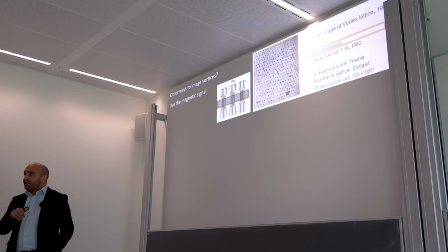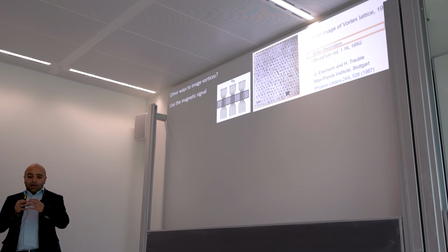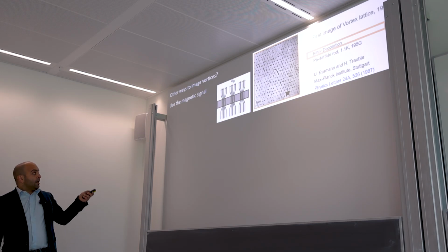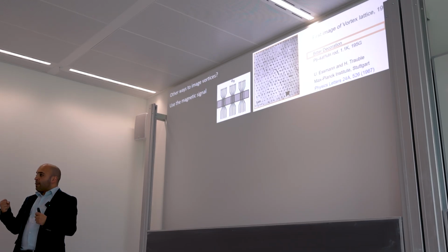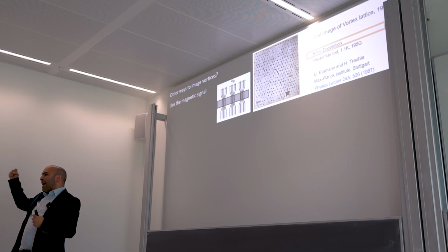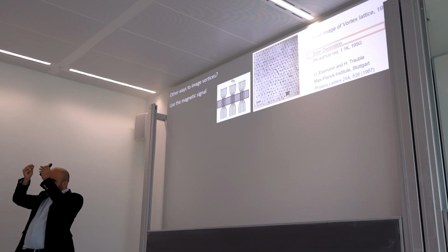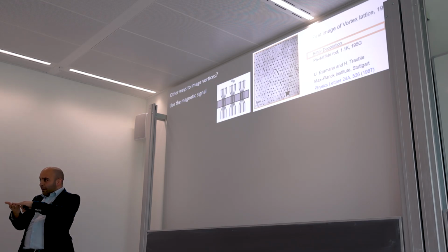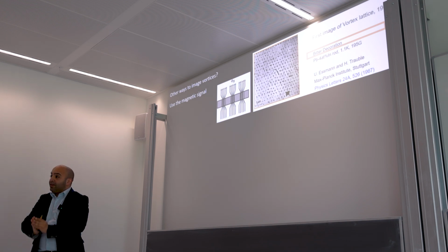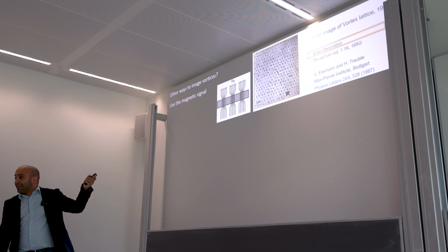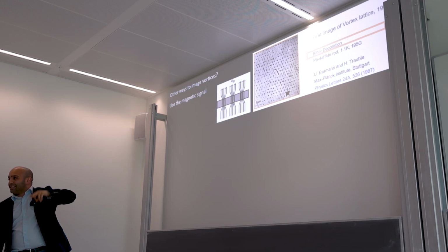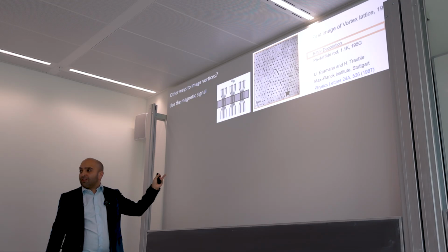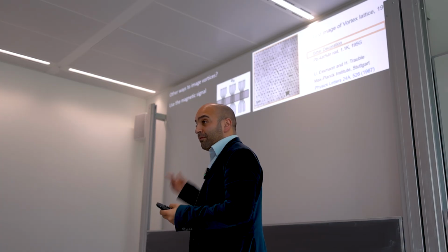So some of you might know this, but basically it's a very clever technique. You have a superconductor, you apply a magnetic field, and you have a flux line wherever there is a vortex. And what you do is you get a very fine magnetic powder, and you spray it into your chamber. These magnetic particles fall onto your sample, but because they're magnetic, they follow the field lines. So you get a higher density of these magnetic particles where you had a vortex. And then you warm it up. Of course, this is a room temperature image. You look at it in a scanning electron microscope and you see this nice pattern. So this was actually the first image of a vortex lattice, and they did it with this technique.